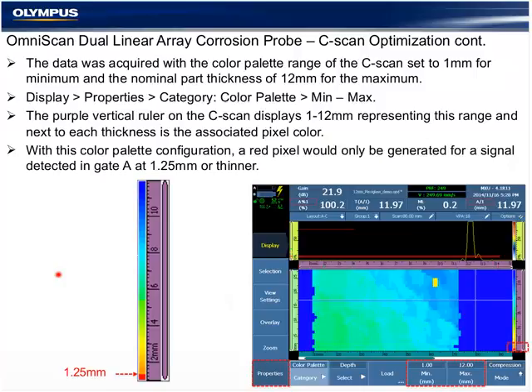The color is going to be our immediate reference in the C-scan for problem areas, low spots, and the nominal back wall. When we configured our color palette a few slides ago under Properties, we configure it for a 1 to 12 millimeter range, which was the nominal thickness of the component.